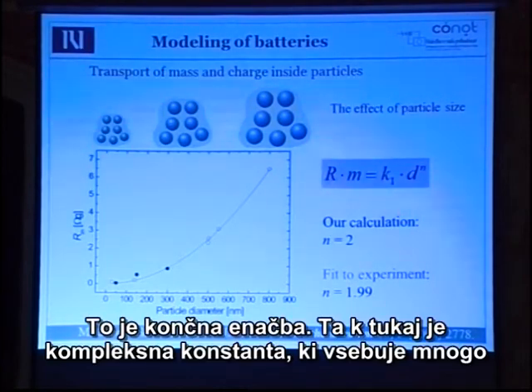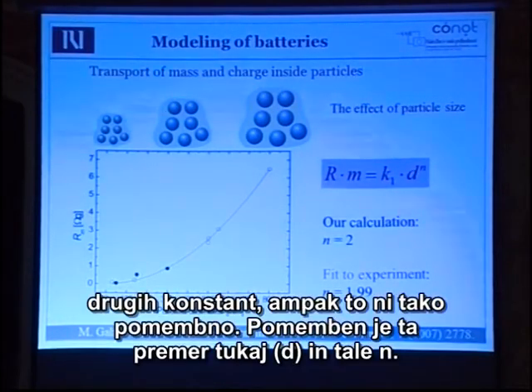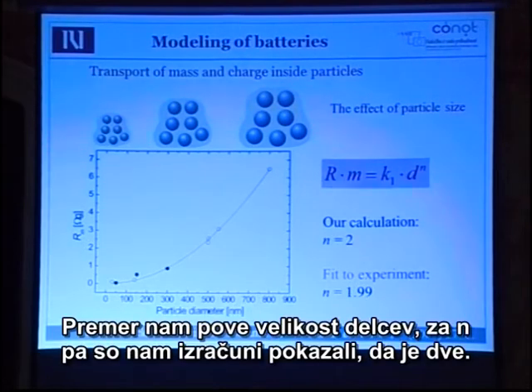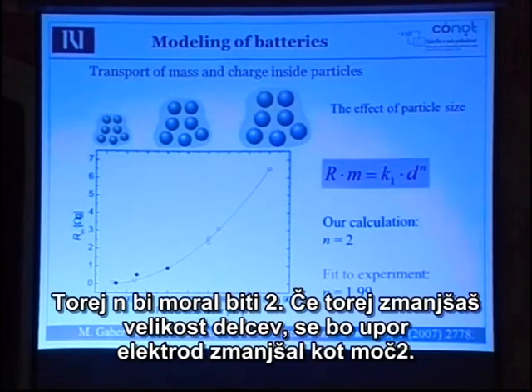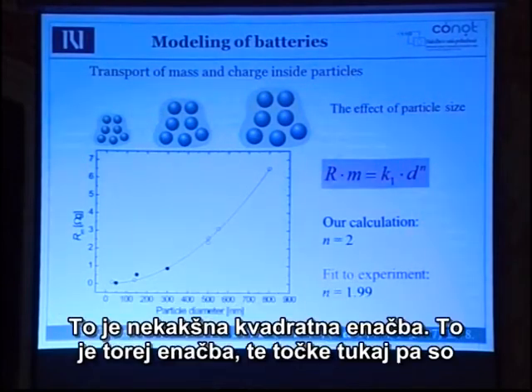This K is a complex constant which has many other constants inside, but it's not important. The important part is this diameter here and this N here. Diameter is particle size. N, in our calculation, is 2. So if you decrease particle size, the resistance of your electrode will decrease as a power of 2. So it's a sort of square equation here.